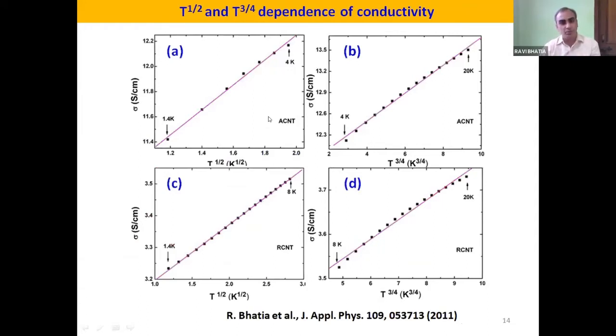Here there is a little bit more description given about the T power half dependence and T power 3/4 dependence. T power half dependence shows the electron-electron interaction contribution, and 3/4 dependence shows the weak localization. The only point here is, for the aligned carbon nanotube sample, the ranges are different. Here 1.4 Kelvin to 4 Kelvin and 4 Kelvin to 20 Kelvin. However, in the case of the randomized sample, it is 1.4 Kelvin to 8 Kelvin. That means a little wider range happens for the randomized samples, but more or less both samples present similar transport properties.